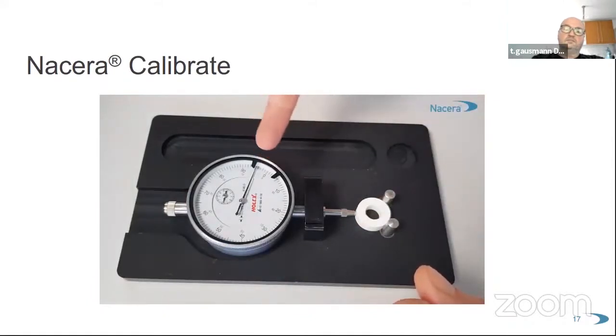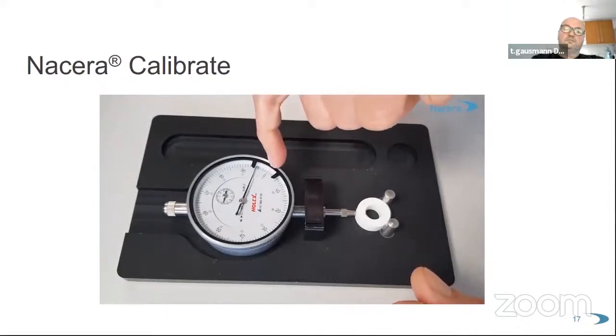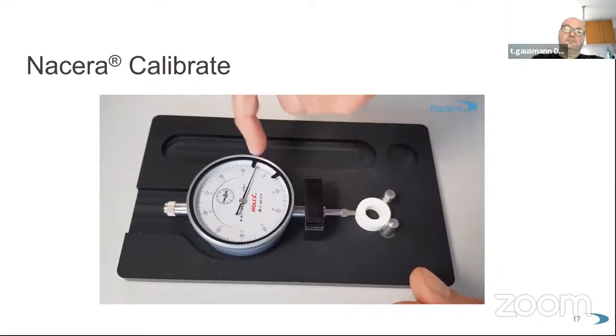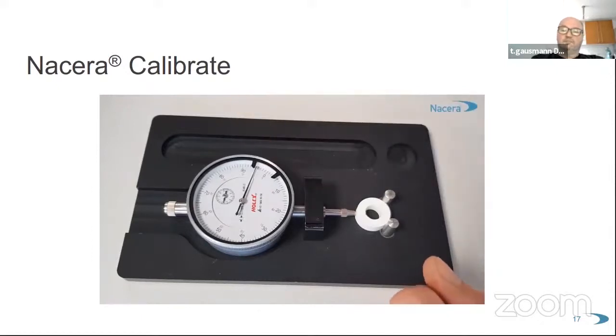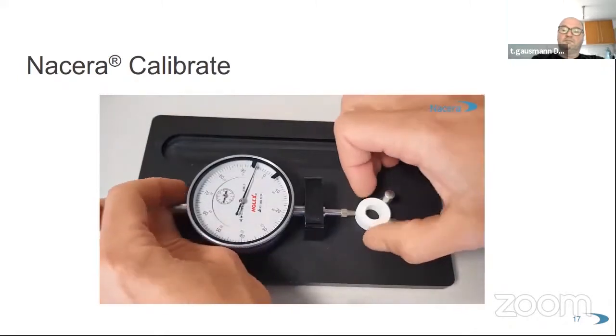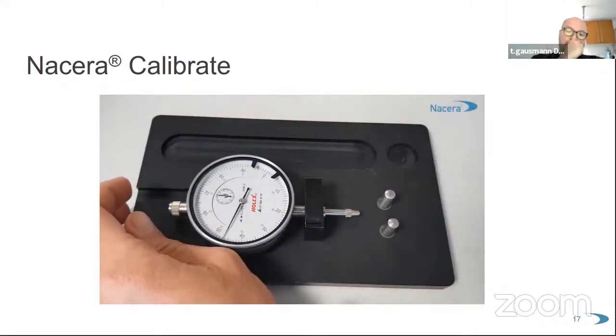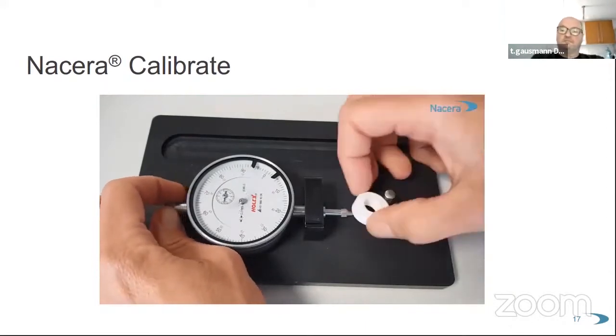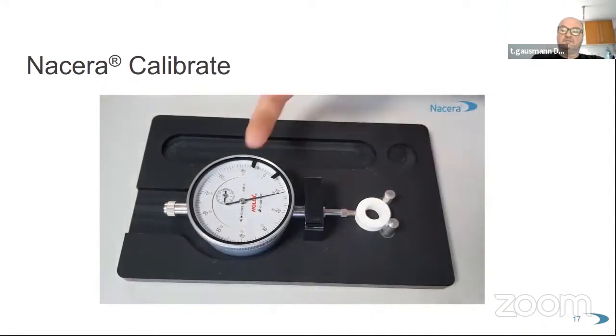Each scale mark corresponds to 2 degrees Celsius, counting from 0 to the left: 2, 4, 6, 8, 10 degrees. Ideally, this value should be 0. If you observe a deviation on the left, like in this case, the temperature in the furnace chamber was too high. The sintering program will be adjusted 10 degrees lower. Let me illustrate by another example. If, on the contrary, the deviation is observed on the right from the zero, like here, 11 scale marks corresponding to 22 degrees Celsius, the sintering temperature will have to be increased by 22 degrees.